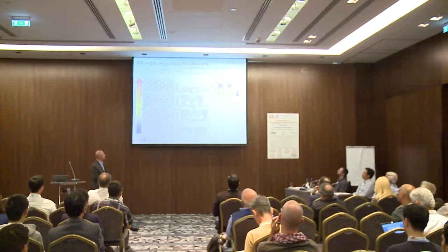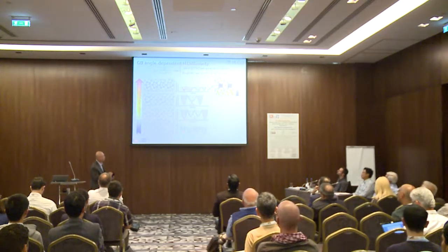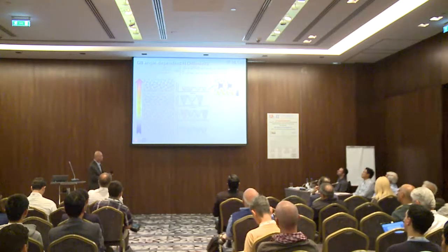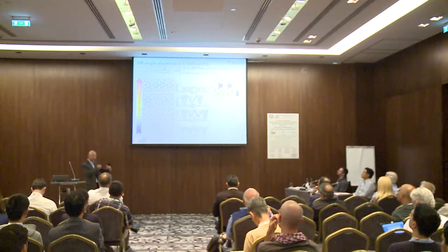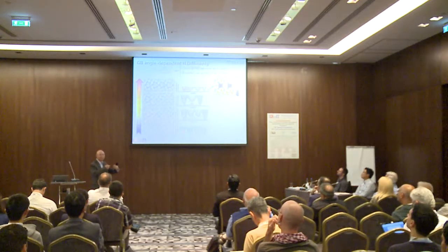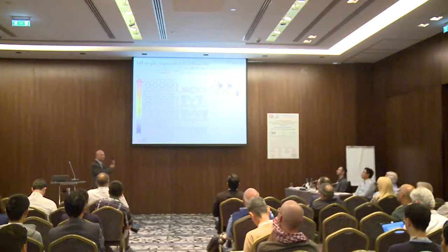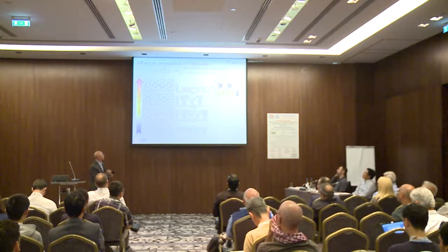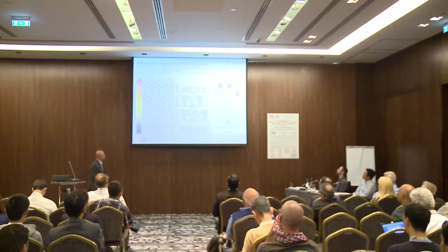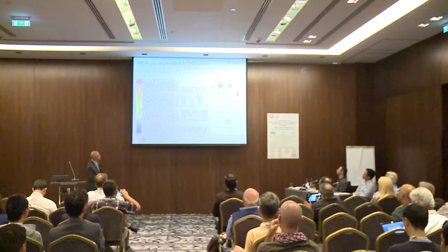So it's a classic picture as expected from this equation. But for the high angle regime, we have shown before that you have the fast diffusion channels. That turns out to be because in this region you have core overlapping, or however you interpret that. And this core overlapping, atomistically speaking, actually distorts all those polyhedra that constitute the grain boundary, and then gets all those paths connected. Okay? So this is basically the reasoning for that fast diffusion.